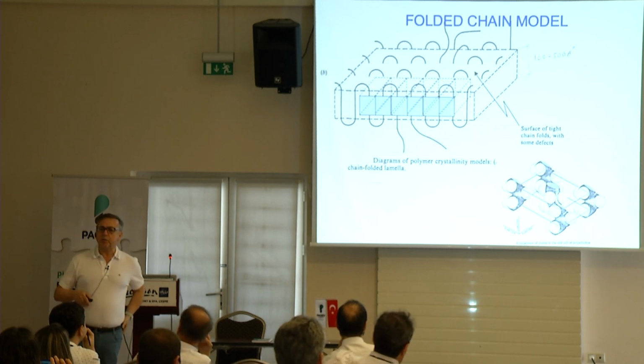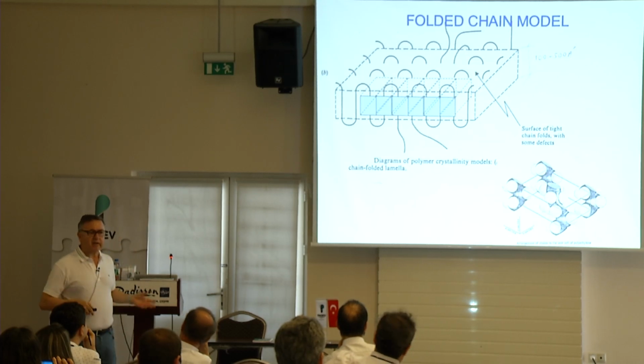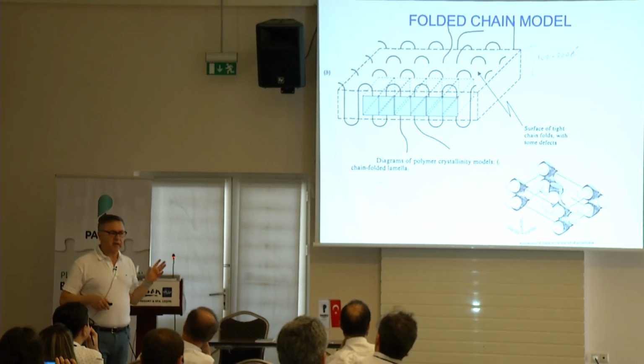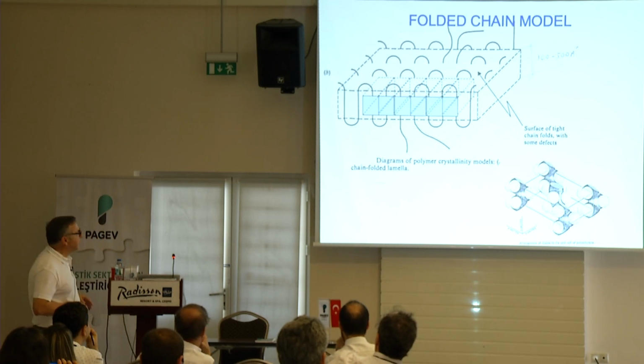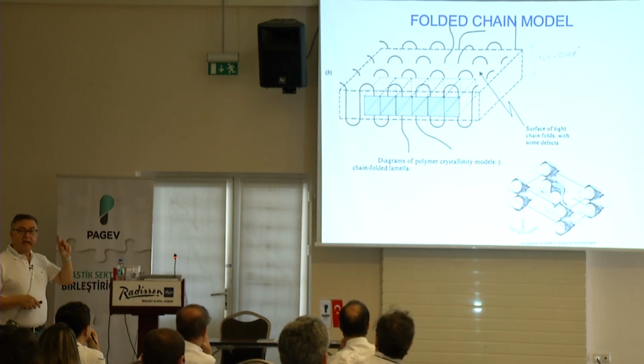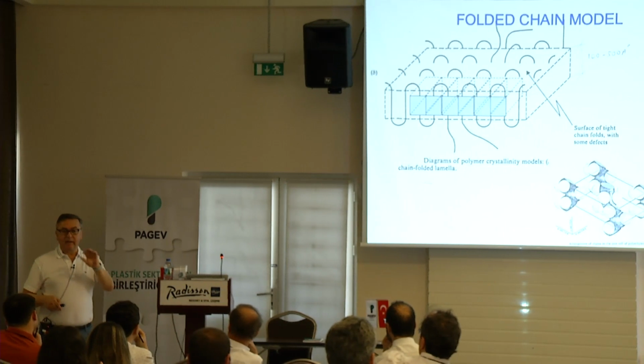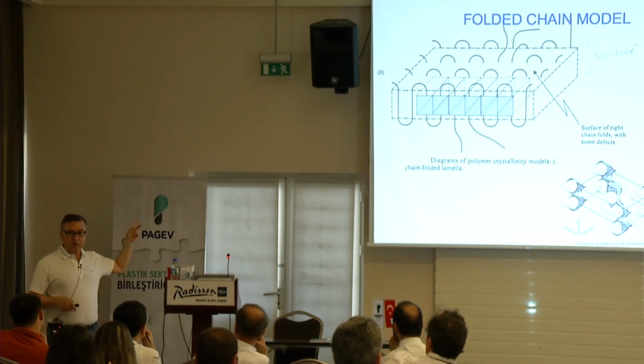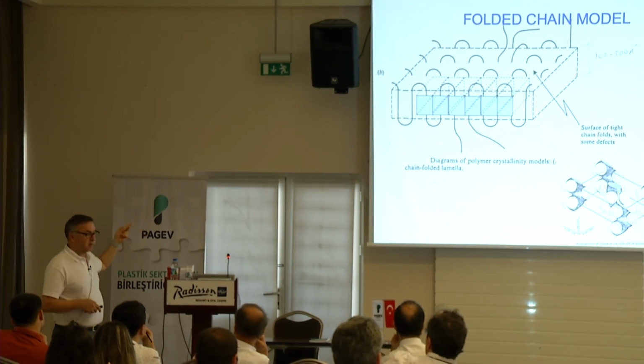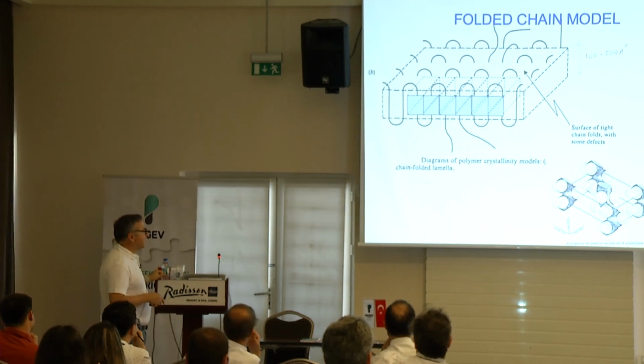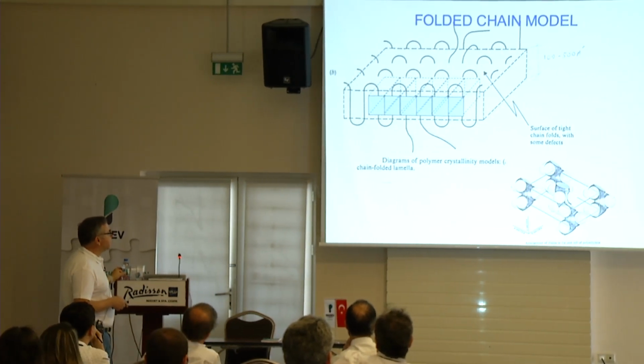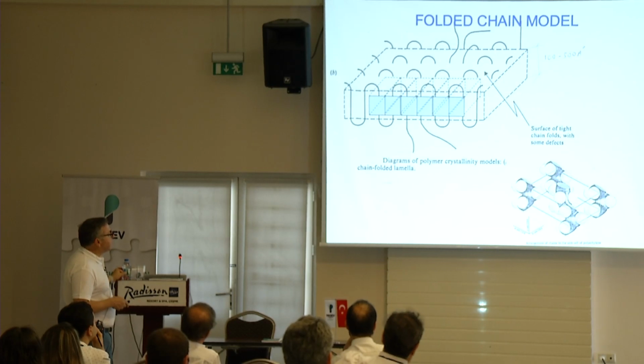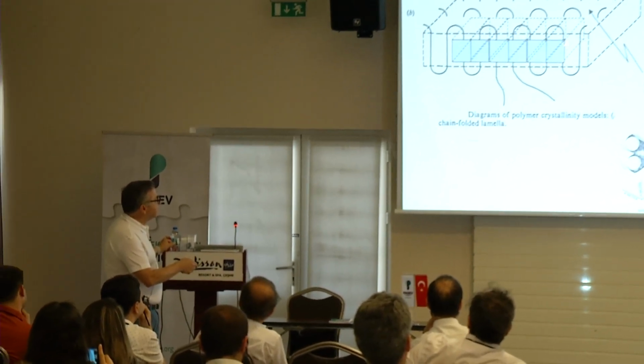Somebody asked a question on polypropylene. Polypropylene is about 100 to 150 angstroms, 10 to 15 nanometers or so. They are that thick. And you can, by processing, actually control the size of this, and we'll talk briefly on what that is. So it's a chain folded model. As you can see, it's much more regular. And once in a while, there is what is called cilia, literally like animal cilia, as biologists sometimes call it.